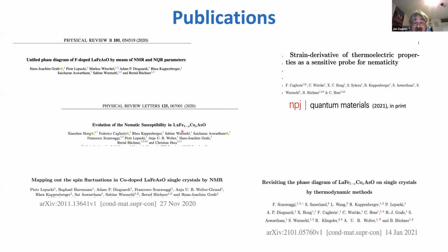Next week I'm up. Yeah, I haven't been paying too much attention to these iron superconductors for a while, but when I was listening to Bernd in the first half, I got a very simple thought. So you look at the nematic susceptibility, and it's basically associated with the electron system, right? You look at the resistivity, and then you have this trouble that you look at the structural phase transition, right? That starts to broaden out. But it seems that the nematic susceptibility is still behaving in a pretty orderly manner, right? It's a nice Curie-Weiss, etc. Now, this may be an obvious thing, and I don't know whether everybody realizes it, but I would rationalize this as the electron system wants to do the nematic transition, right?